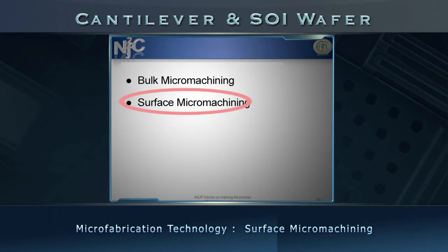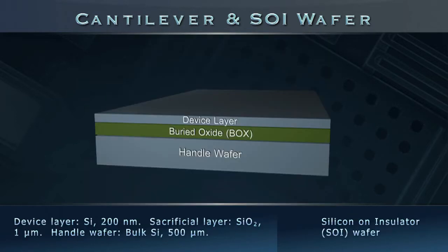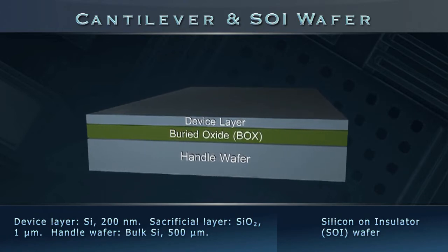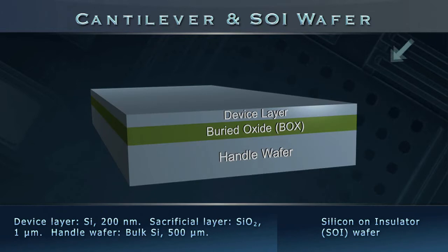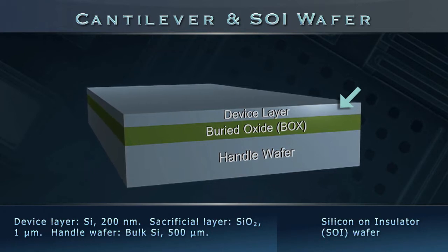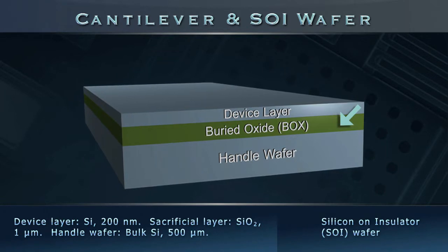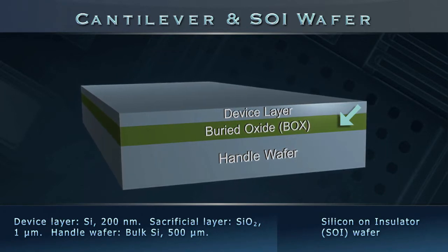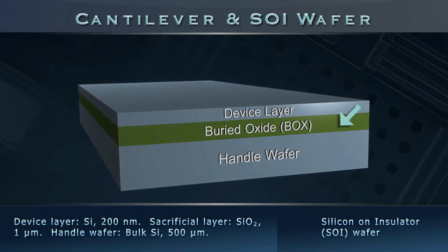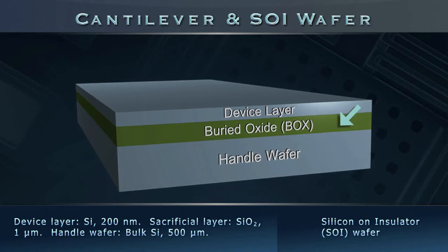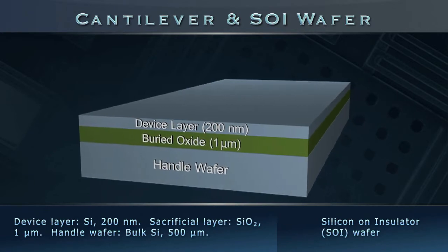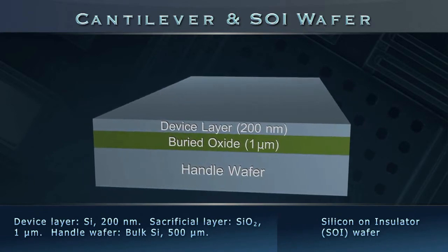This approach requires a silicon-on-insulator or SOI wafer, which is a 3-layer material stack composed of the following. On top, a mechanically active device layer made of prime quality silicon. Intermediately, a buried sacrificial layer of silicon dioxide or BOX. This electrically insulating intermediate layer is selectively etched. At the bottom, a support wafer or handle of bulk silicon. Our SOI wafer has a 1 micron thick silicon dioxide layer buried under 200 nanometers of silicon layer.